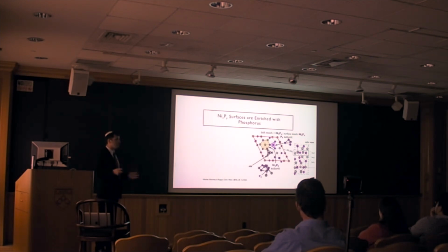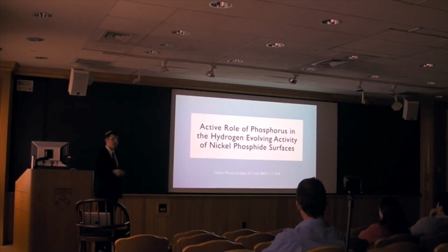And so we see nucleation of phosphorus phases on the surface, which is a very new thing, and hasn't been observed for oxide systems because oxides can't form stable connected chains of oxygen, whereas phosphorus and its neighbors on the periodic table, sulfur, they can form extended chains in their elemental form. And so that makes their surface reconstruction behavior very interesting.